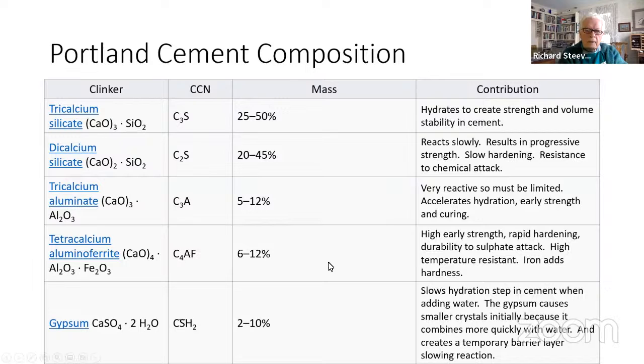So you can see here these different elements or these different compounds that you add. The last one in the list I thought was pretty interesting. This gypsum that you add is used to slow down the curing of the concrete or of the cement, and it does that by reacting relatively quickly initially. It results in high initial strength of the cement, so it keeps it from flowing and that sort of thing, but it slows down the formation of this tricalcium aluminate, and so allows the cement and the concrete to flow better when you're forming it in molds or in forms.